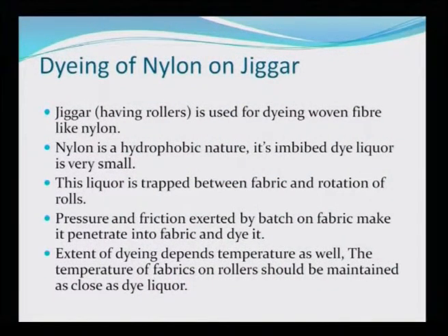But in general, nylon is hydrophobic in nature, that is, it is not water loving. Therefore, the dye liquor that goes into the fabric by the mode of adsorption is very small. But this liquor, meaning the dye solution, gets trapped between the fiber and the rotation, and therefore remains there for some time in close proximity with the fabric, and that is what allows it to get adsorbed. Once the adsorption takes place, it starts diffusing inwardly to get into the core.